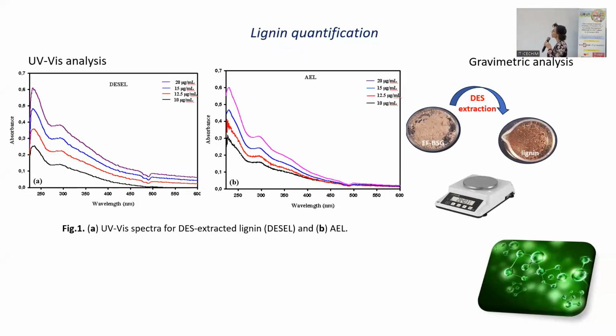For lignin quantification, we use spectrophotometric methods. The characteristic wavelength of lignin was 280 nanometers. These two spectra have much more similarities. And this method was compared with gravimetric analysis. And there are comparable results.